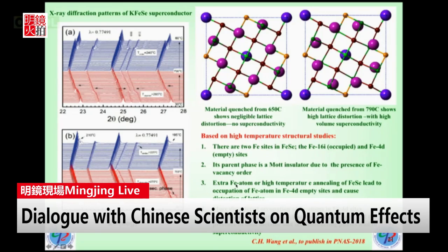But when I have an extra iron atom or high temperature heat treatment, it becomes random, then the 4D site starts to be occupied. And this occupation leads to electrons, just like what I said earlier, being taken out of a certain atom and giving you the carrier. So originally empty, now you start to fill, then you start to see the carrier, and superconductivity emerges from that.